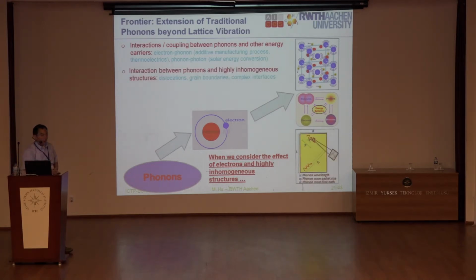And then phonons can also interact with highly inhomogeneous structures. For example, the very common case is the grain boundary, right? This is very common. And in recent years, people found that if you introduce dislocations inside the materials, you can reduce the thermal conductivity without significantly decreasing the electronic transport, right? Which is very beneficial for thermoelectrics.